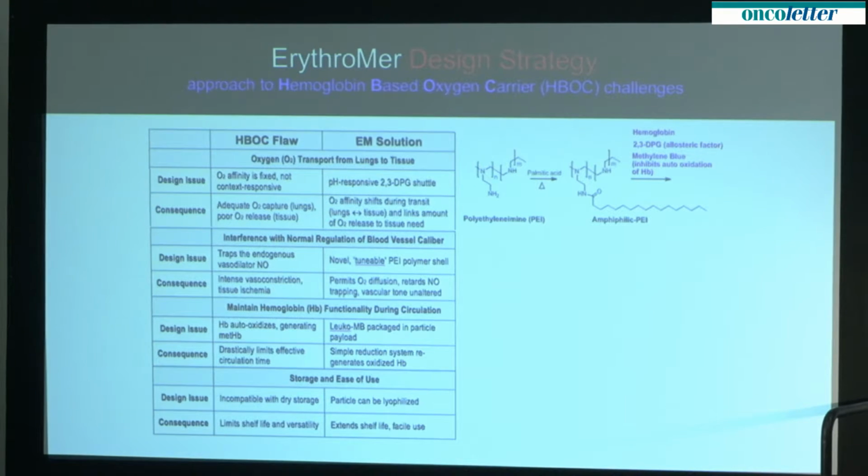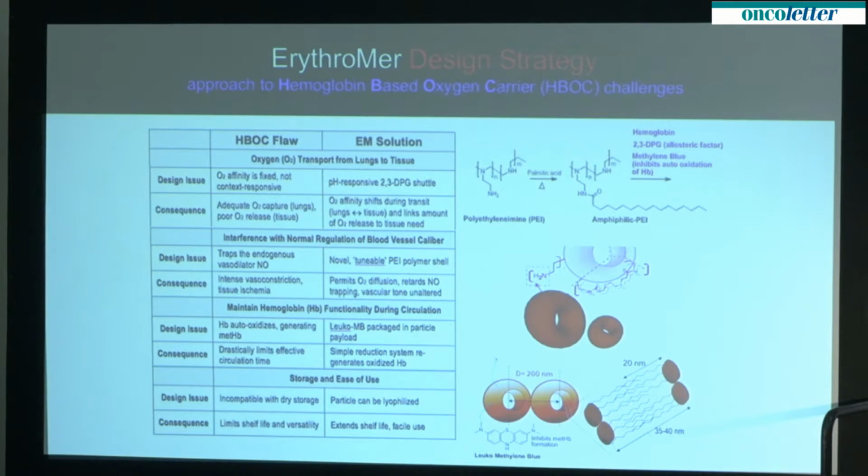A molecule that was designed to imitate the normal components of a red cell membrane is put in a vessel with the payload components. It self-assembles into a toroid about 1/50th the size of a red blood cell, and at the end of synthesis, the surface is cross-linked to improve particle stability and to develop the selective diffusion barrier for nitric oxide.